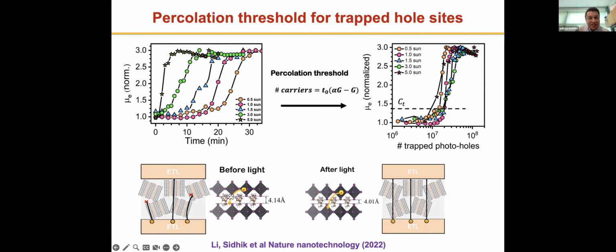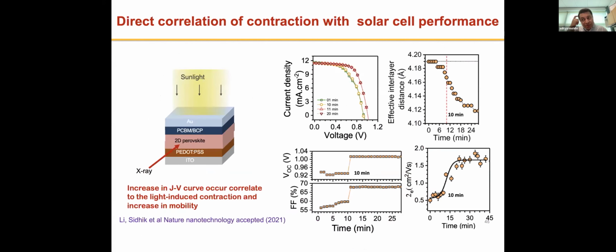Okay. Now, finally, I just have a couple more slides in order to really show that this was really happening, and this was really responsible for these jumps that we were seeing in the solar cells, jumps in efficiency, in voltage and fill factor. We performed an in situ measurement again. We took a device and mounted it, we performed the same measurements and monitored its structure as we were monitoring also its photovoltaic properties.